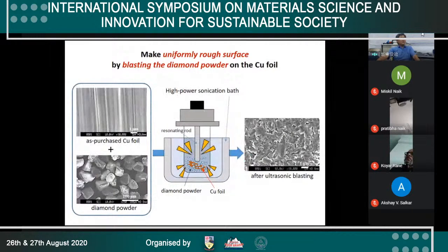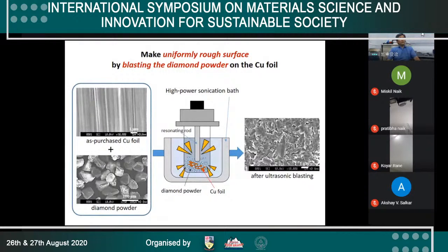So we tried to make a uniformly rough surface. It's a little bit strange wording. We made a uniformly rough surface by blasting diamond powder on the copper foil. We put the diamond powder on the copper plate and do strong, high power sonication. You can see the result. After the ultrasonic blasting, we can get a rough surface, and we then grew the graphene. The result is next.